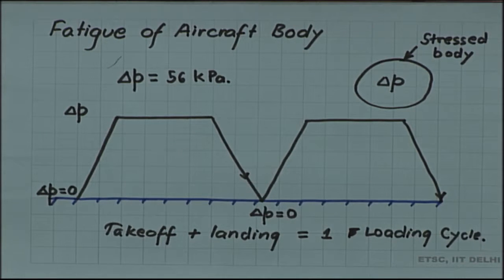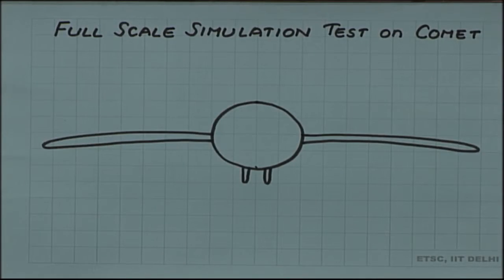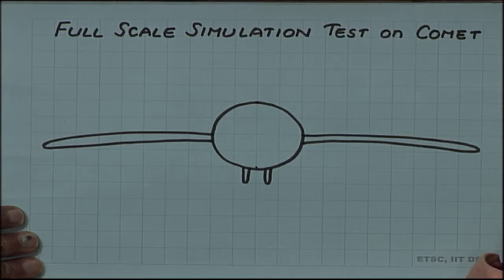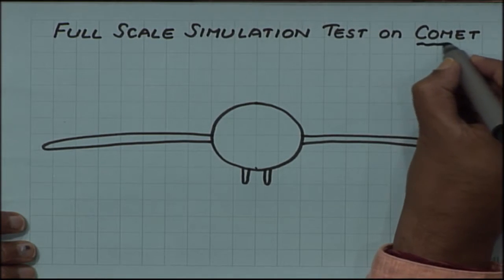But engineers and investigators were of differing views at that time. Some thought this kind of pressurization and depressurization cycle would lead to fatigue failure of the aircraft body; some thought it would not. In fact, the company itself tested a small piece from the aircraft material and declared that fatigue is not a problem. But the investigators of the crashes were not convinced, so they decided to do a full-scale simulation test on fatigue, a full-scale fatigue simulation test on Comet.